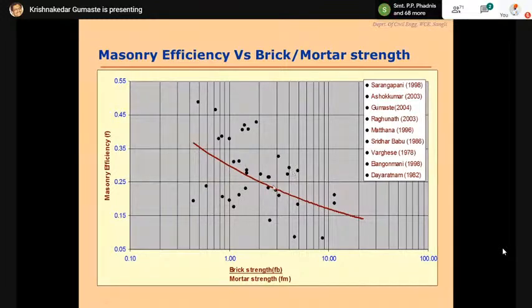And you can see that the variance is quite a lot, the standard deviation is quite varying. This is basically because the material of the brick itself has a large variation. If you test about 15 bricks, the standard deviation could go anywhere up to about 30 to 35%, depending on whether it's a wire cut brick, a table molded brick, or a country brick.